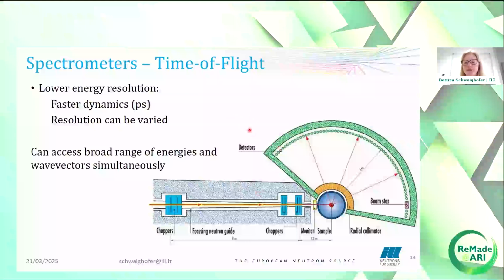Here I'm showing a schematic diagram of a time-of-flight spectrometer at the ILL, IN5, which uses a monochromatic beam, which is pulsed by these choppers, and it hits the sample at a certain time. It is then scattered and the neutrons fly to the detectors, where they are measured, and the time of flight can be determined. This gives us a three-dimensional spectrum of the detector position, X and Y, and the time, which can be converted to the dynamic structure factor.